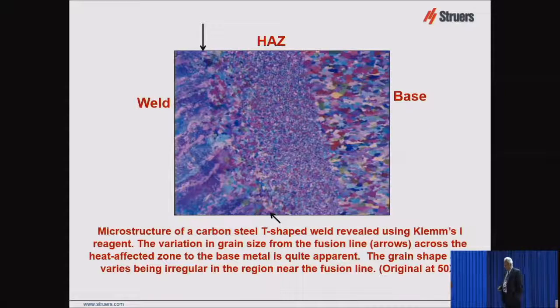Here's a carbon steel with a T-shaped weld, and we're etching it with Klemm's. The weld metal is on the left here, this is the heat affected zone, and here's the base metal. And the color etch like this really allows you to well define the nature of the ferrite distribution.